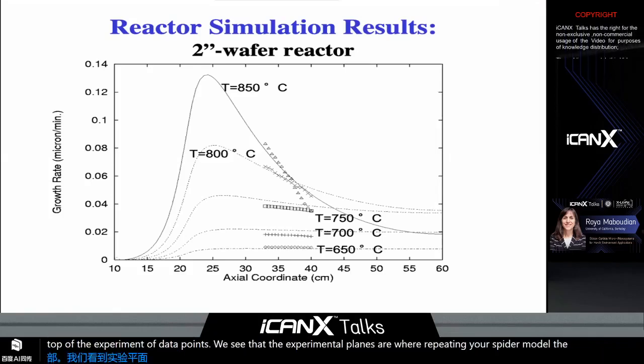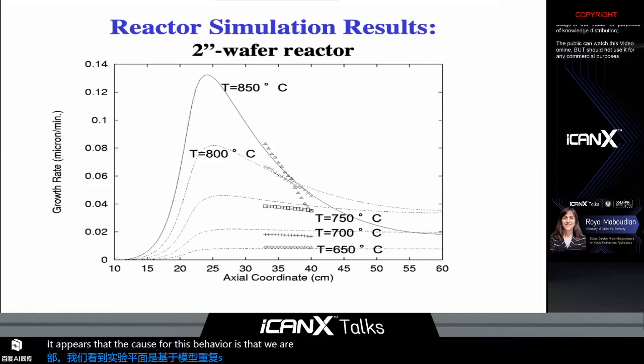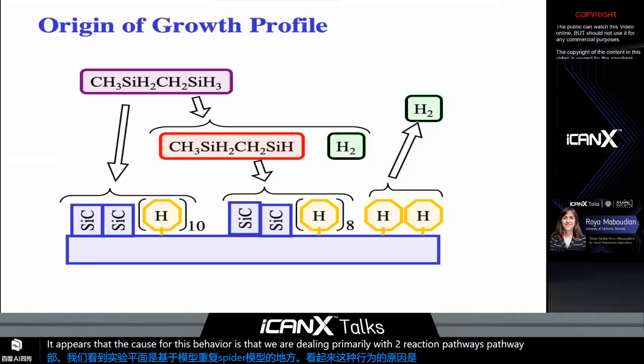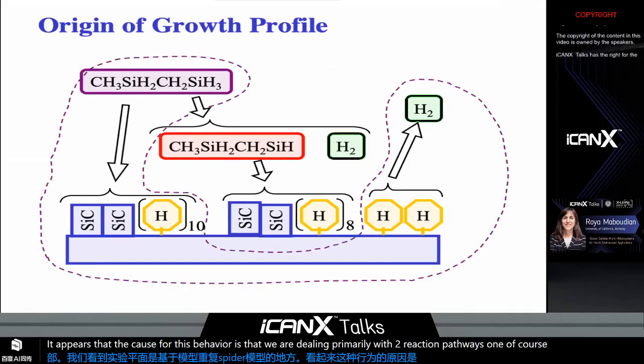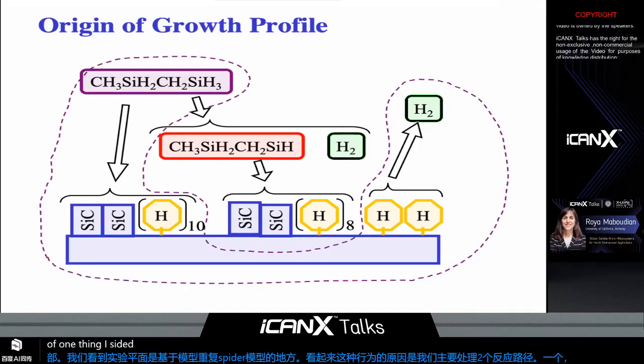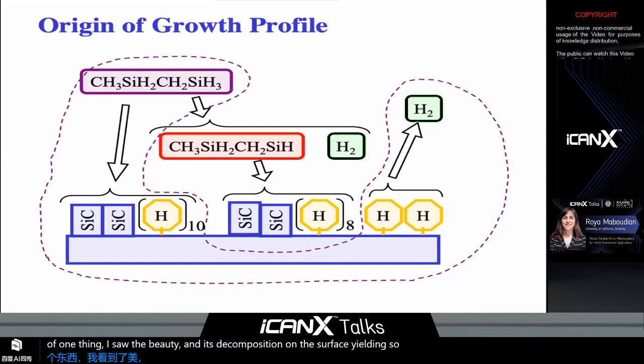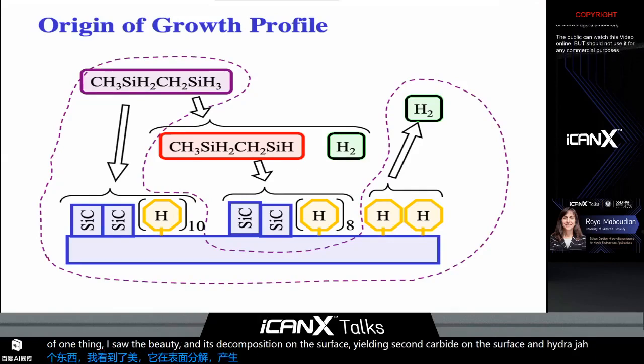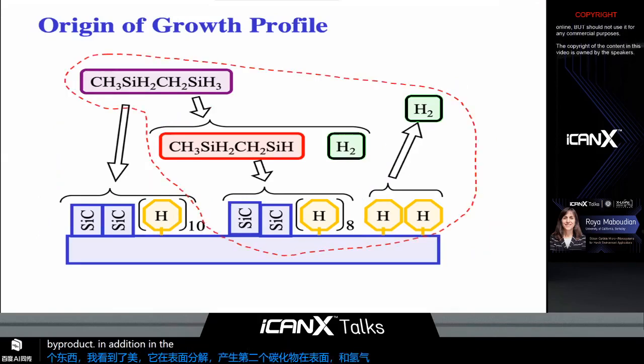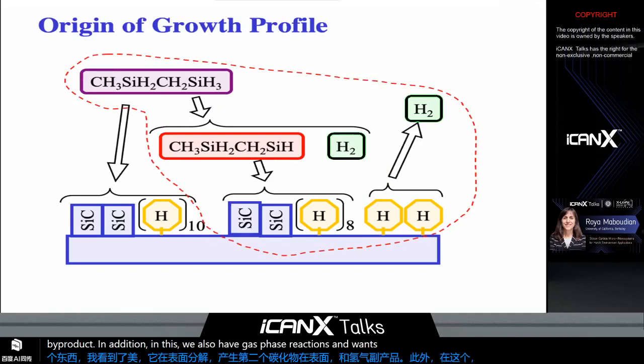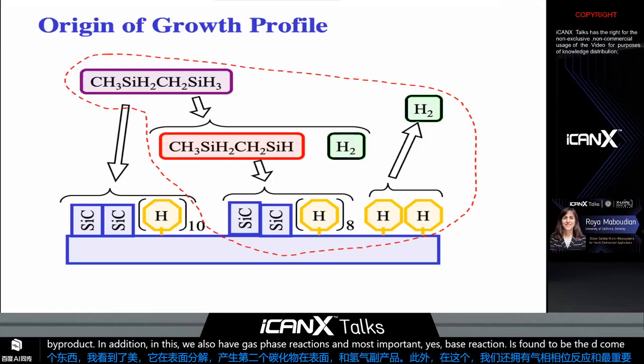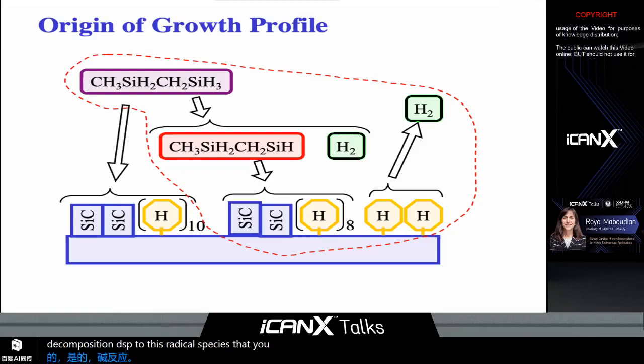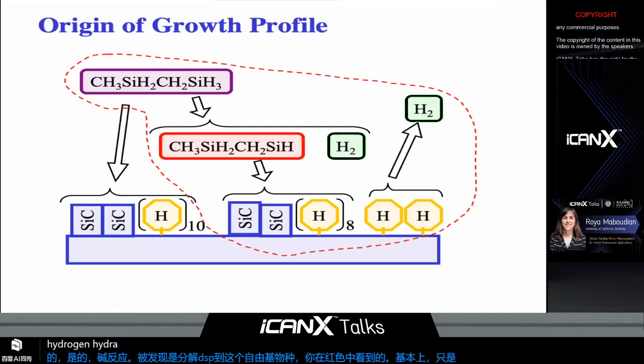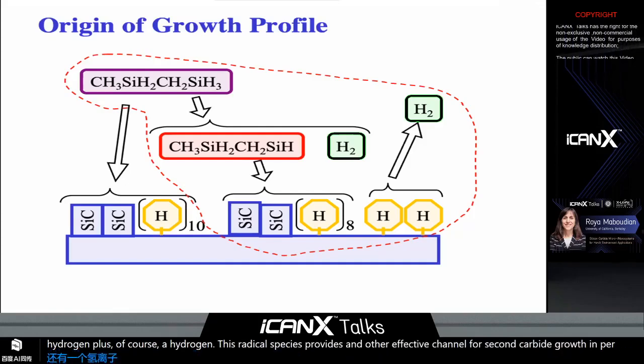Based on the model, it appears that the cause for this behavior is that we are dealing primarily with two reaction pathways. One, of course, is the adsorption of 1,3-disilabutane and its decomposition on the surface, yielding silicon carbide on the surface and hydrogen as gaseous byproduct. In addition to this, we also have gas phase reactions. The most important gas phase reaction is found to be the decomposition of DSP to this radical species that you see in red. Basically, it's a DSP molecule with the end silicon missing two of its hydrogen, plus, of course, a hydrogen. This radical species provides another effective channel for silicon carbide growth, in particular at high temperature.